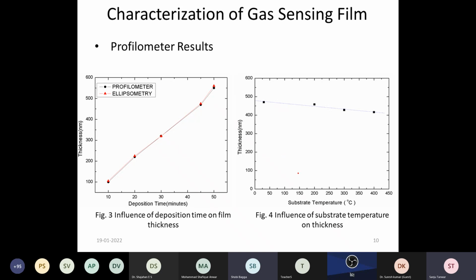For the second set of experiments, we varied the substrate temperature from room temperature to 400 degrees centigrade, and we can say the thickness is almost constant, but there is a very slight variation. That comes because whenever we deposit at a high temperature, the packing density of the film increases, because the material coming onto the substrate may go to the more thermodynamically stable side. So packing density is going to increase a lot. So there is a slight variation in the thickness with the substrate temperature. When we increase the substrate temperature, the thickness is slightly reducing, not too much. That is the first part: the parameters which we have varied, and their effect.